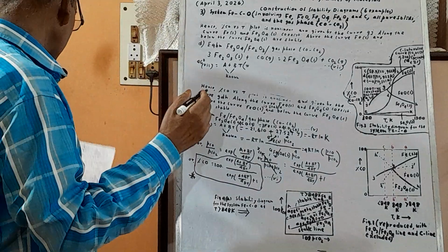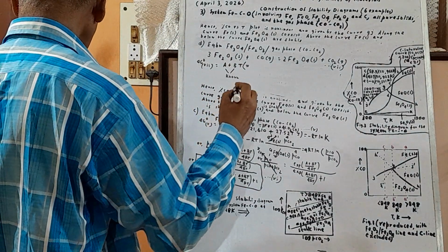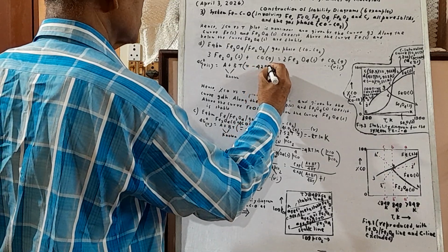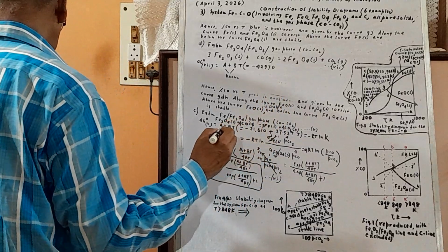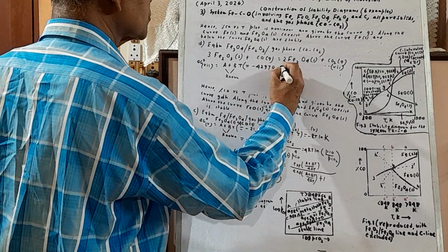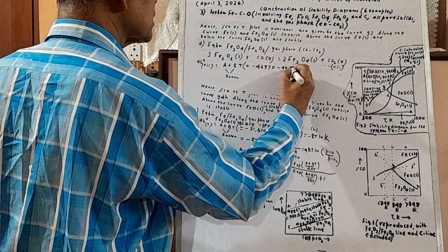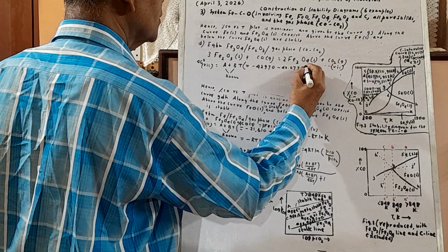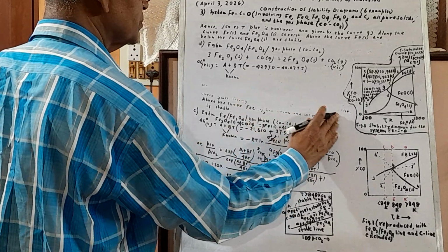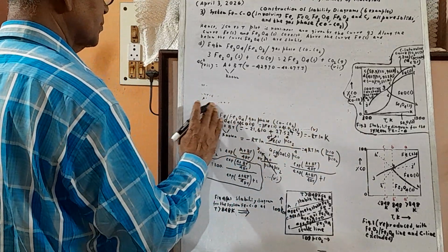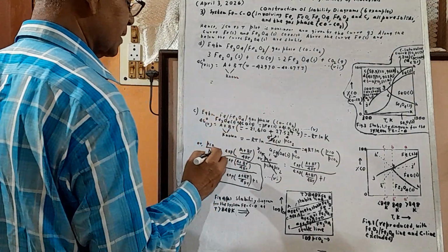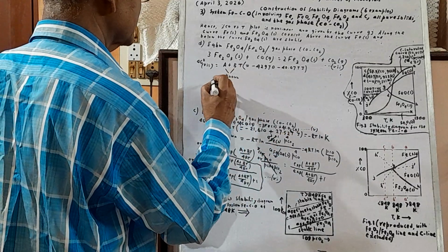Okay, A plus BT is what? Let us pick up this: minus 42970. So for reaction 7, delta G0 is minus 42970, minus exothermic as I told you, minus 40.07 T joule. Okay, this is what? Remove this, no problem. This is what? Remove this. This is minus RT ln K.